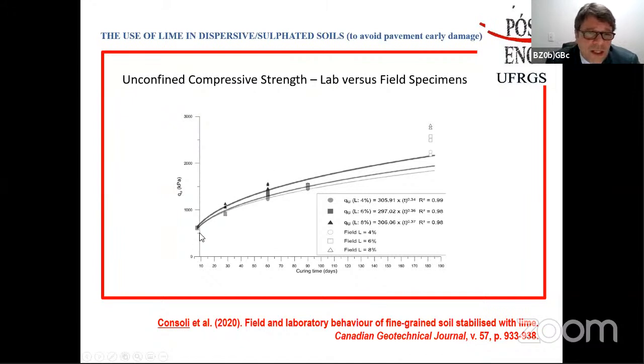Another thing that's quite interesting is that we carried out tests in the lab, and also collected specimens from the field, and we were able to see how the unconfined compressive strength changed with time. Here we have, let's say, after 30 days, 60 days, 90 days, and also 180 days, that the strength was increasing with time. These results here are from the lab, and these here are from the field. Using these results, we tried to see the trend, and we saw that in the field it was even a little better than expected. It means that the mix in the field was quite well done, I would say.